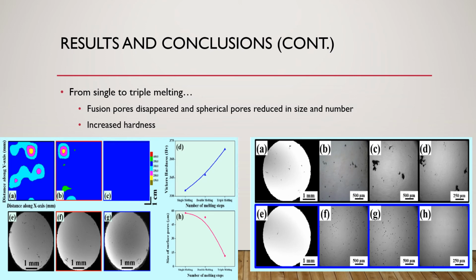There are two categories, one being the lack of fusion pores, which have an irregular shape and are dependent on the SLM process parameters. The other category is a metallurgical pore with a spherical shape, which forms due to the presence of absorbed or entrapped gases. Increasing the melting steps vanished the fusion pores and the spherical pores were reduced in number and size, as observed on the lower right image.